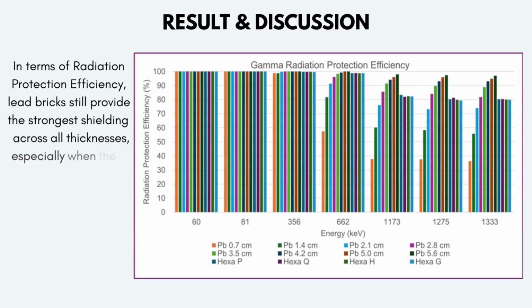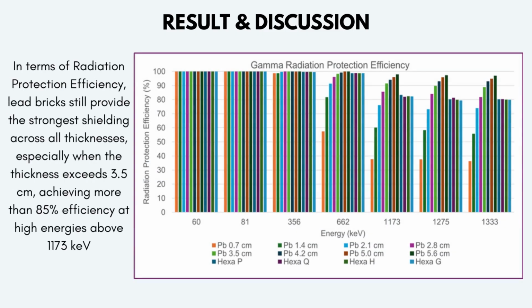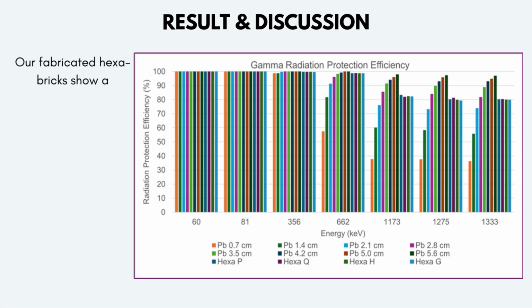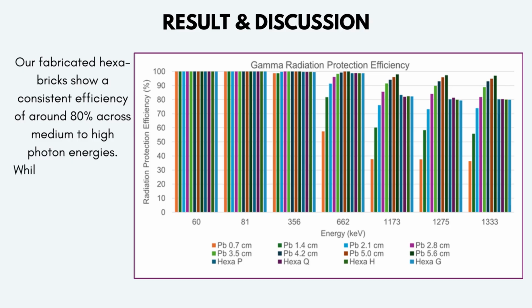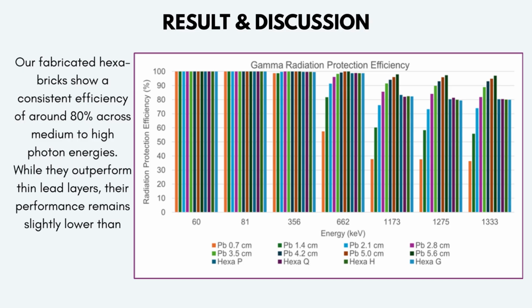For the result and discussion, the radiation protection efficiency shows lead bricks still provide the strongest shielding across all thicknesses, especially when the thickness exceeds 3.5 cm, achieving more than 85% efficiency at high energies above 1173 keV. Our fabricated hexabricks show a consistent efficiency of around 80% across medium to high photon energies. While they outperform thin lead layers, their performance remains slightly lower than thicker lead bricks.